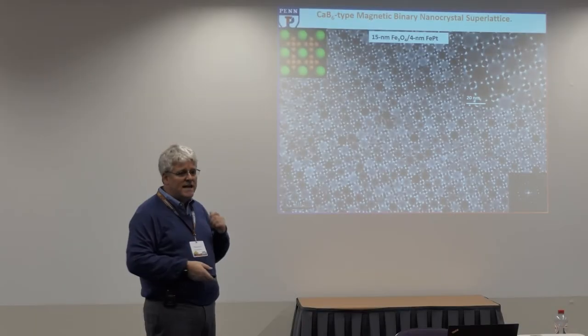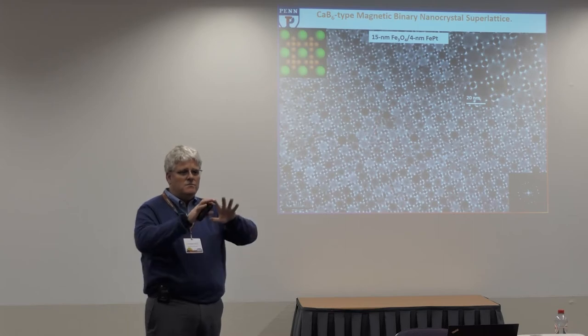But in order to get the maximum energy density, you actually want both of those parameters to be large values, high values. So this is what's called an exchange spring magnet. If you measure the magnetic properties of the separate components, and then you couple them together through this process, you get about a 30% increase in the energy density of the magnet. And that's because the hard magnets exert a restraining force on the spin system of the higher moment constituents.